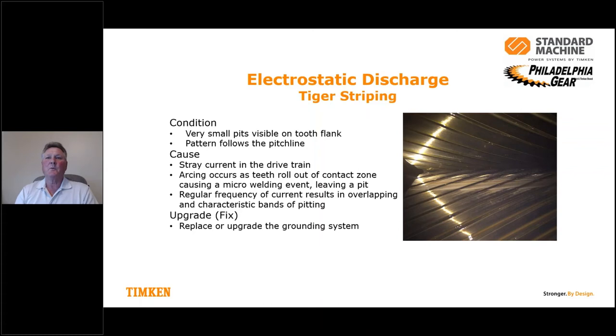It has a welding process, and when it rolls out, it pulls that weld. That welded piece gets torn apart, and that leaves a pit. And if it continues, you'll have overlapping pitting in it, and it starts to cover itself up. So there are always characteristic bands. So you can see that something looks very common between all the gear teeth. So you've got to replace or upgrade the grounding system. You've got to find out where the source of electrical charge is coming from.